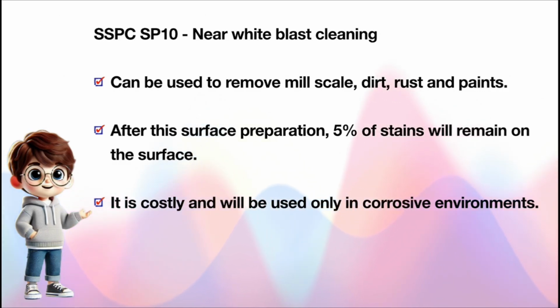Near white blast cleaning. It involves removal of oil, grease, dirt, rust, mill scale and previous coatings. Any remaining staining is limited to a maximum of 5% of the entire surface area, which means that after cleaning the surface area of steel, you can only find a maximum of 5% of the stains which remain. SSPC SP10 is often used when a high level of cleaning is required, such as in severe corrosive environments. It is very costly.